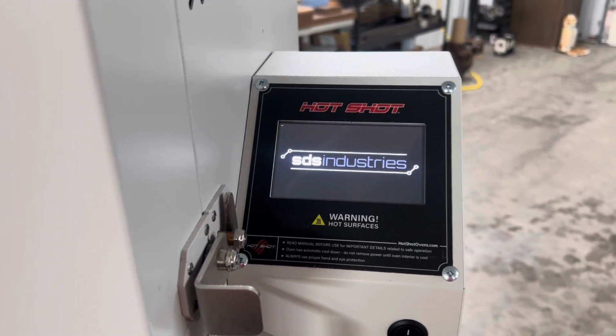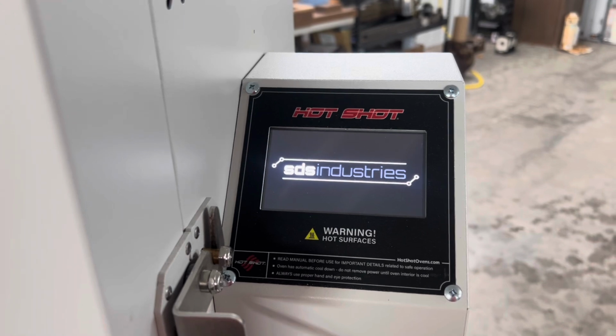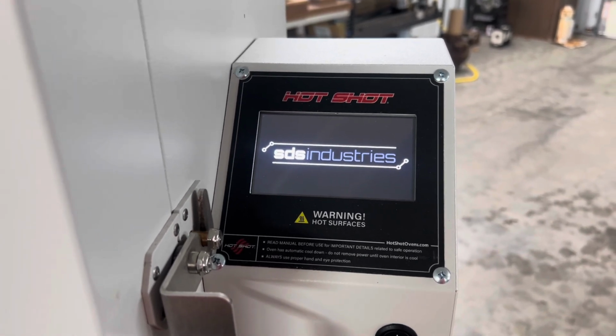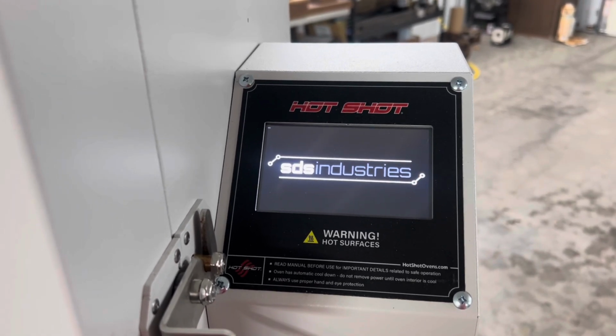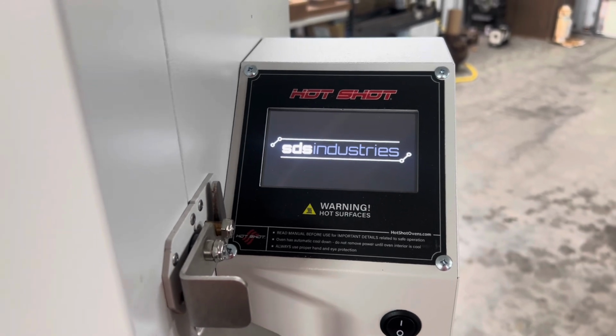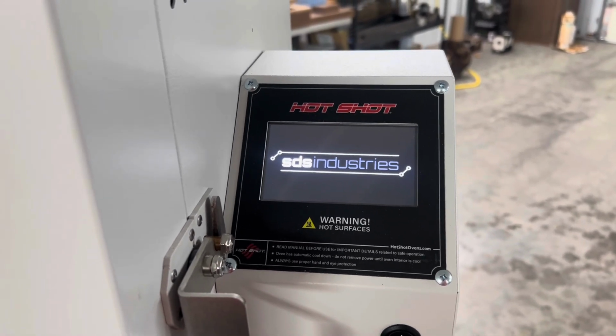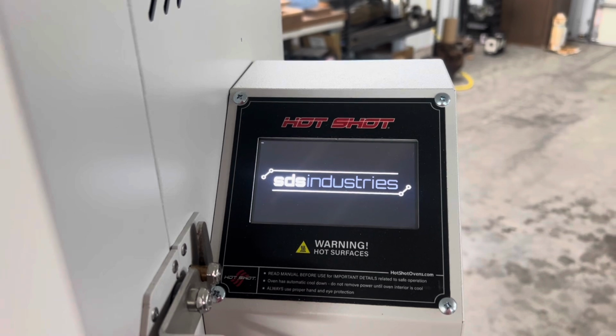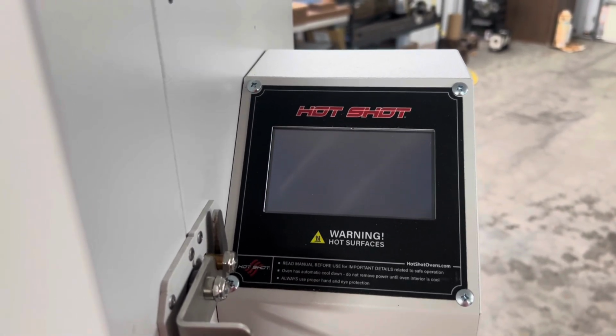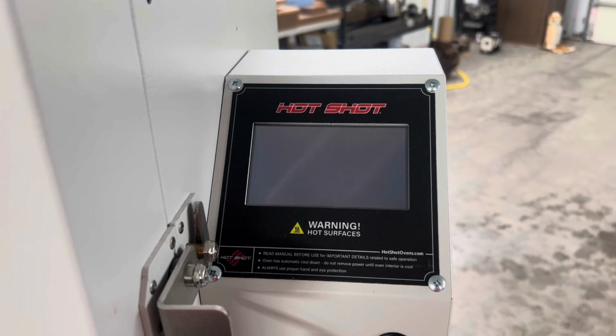And I've actually already got CPM 154 programmed into this oven. So what it's going to do, it's going to ramp up to, I think, 1450 degrees, hold for 10 minutes, and then it will ramp on up to 1950 degrees and hold for 20 minutes. At that time, an alarm will go off, and then we will bring the blade and back spring out, and